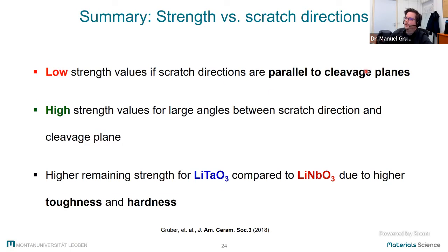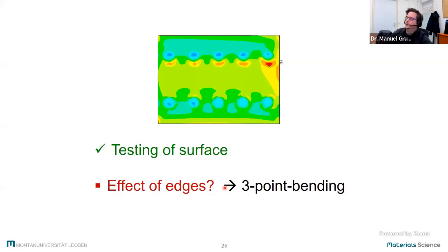results, we have low strength for any defects parallel to cleavage planes, high strength values for any other configurations. And the reason why lithium tantalate is much stronger compared to lithium niobate has to do with the toughness and the higher hardness of the lithium tantalate material. So this was for the experiments on the surface, but as I showed you before, we also have to worry about the high stresses at the edges of the material. So we also did some experiments with three-point bending to see what kind of effects the edges of the material have, and if we have to worry about the cutting process.